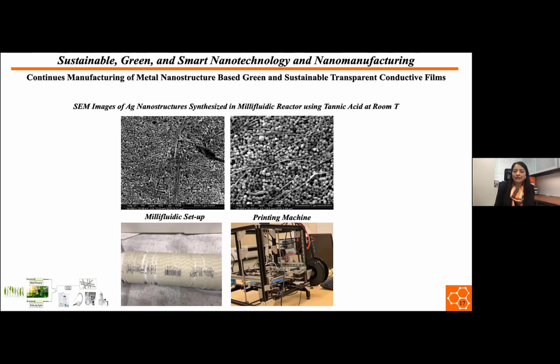Here you can see, for example, a setup that Sina has used to have a segmented flow reactor, either using silicone oil or air, to reduce the coating of silver nanostructures inside the tubing, because we believe that this coating, or fouling, that we get has an adverse effect on the size and morphology of the silver nanostructures that we are producing. And ultimately, when this design and its reaction condition is optimized, we are going to connect this continuous system to the printing machine, which is available in our lab, to be able to continuously produce silver nanostructures and print them on flexible substrate.